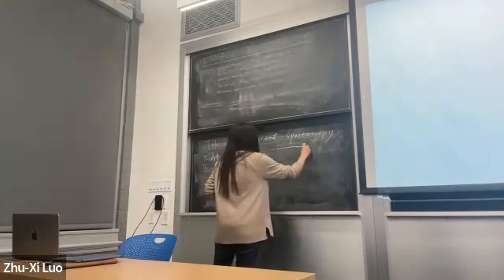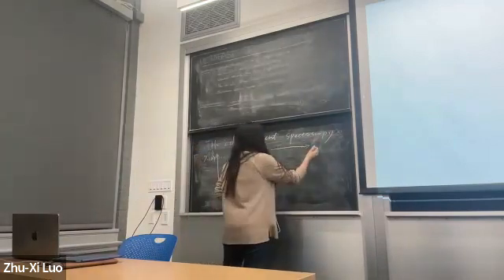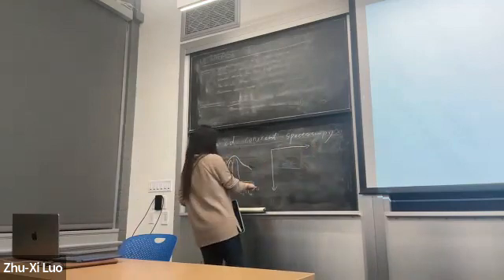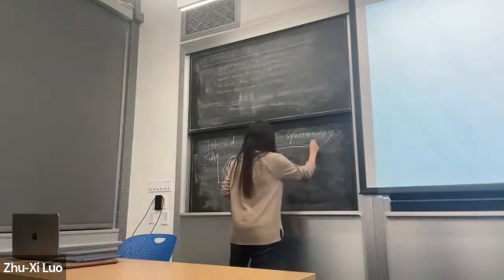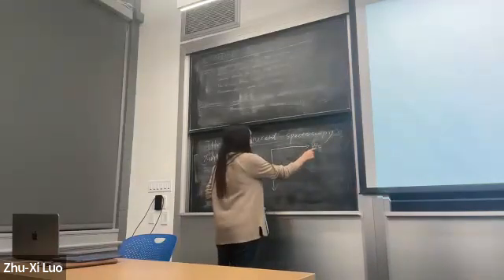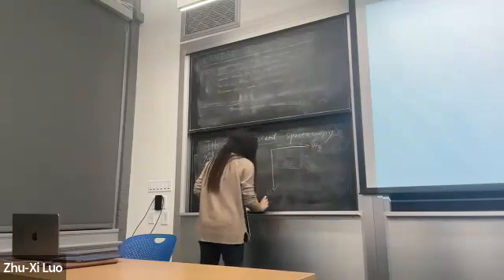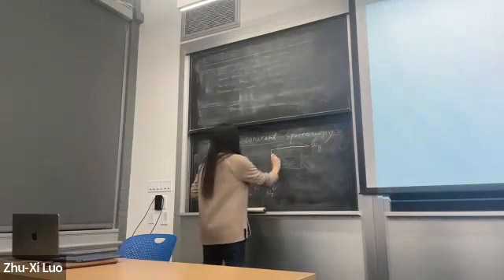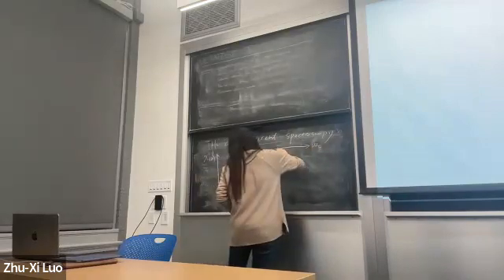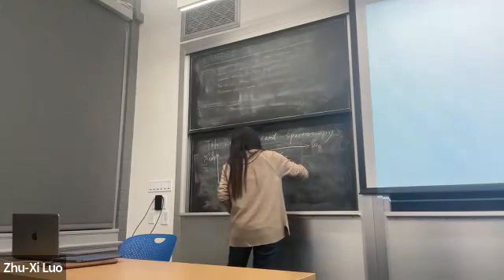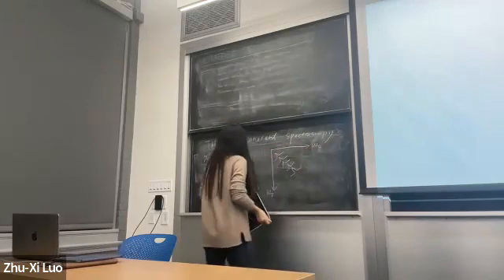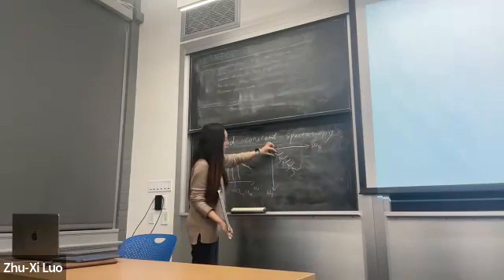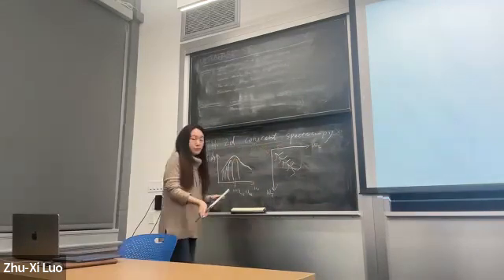What that 2019 paper proposed is, instead of doing a one-dimensional thing, you do a two-dimensional color plot. You have two frequencies. You perturb the system with some light, and then detect it with some other light. And then you have two frequencies. You can do a plot. You still have a convolution. You have the congestion basically along the diagonal. It's a very bad drawing, but then you can see the intrinsic spectral properties such as the line width, the lifetime, by looking at the anti-diagonal direction.